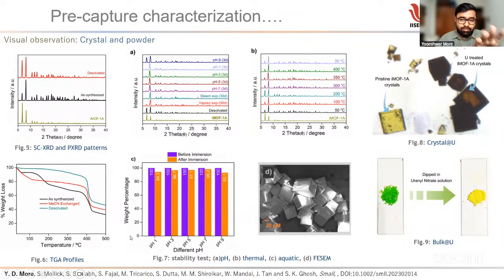What we did, we first try to understand whether there is MOF leaching. Okay, the physical methods we have done. Let's go for the chemical method. So suppose we put the MOF, 100% amount, say 10 milligram, in pH 1, and then we recovered it after a certain time, let's say 3 days. We recovered the MOF and we measured the amount. It was like 94.3%. It means the MOF leaching in the acidic liquid medium is not that great. It means the MOF stability is quite great and leaching is to a lesser extent.